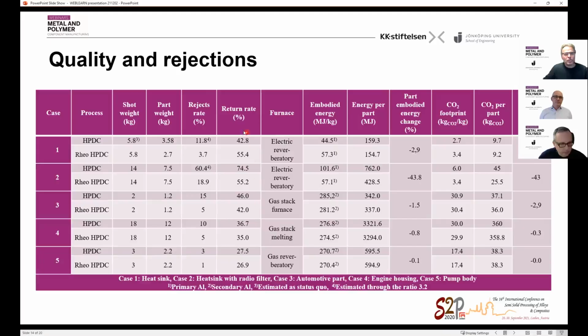So these are numbers that you would find from foundries. And if we take a serious look at this, of course you have certain amounts of embodied energy per kilo and per part. And the interesting portion here is that the embodied energy per kilo actually goes up if you have a part reduction and do not change your gating system. But the embodied energy per part goes down. And it's the same thing with the carbon dioxide footprint. So it's also important how we measure and understand what we actually do in the processes.